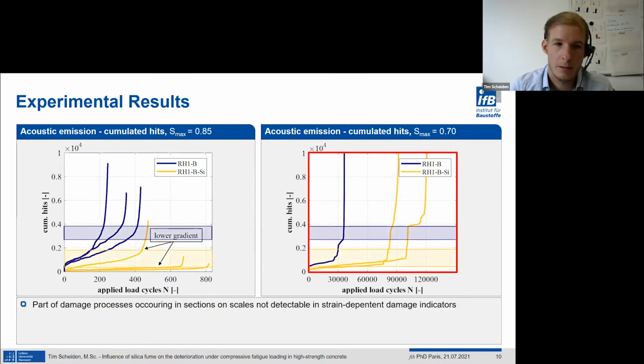In addition to the stepwise curves for the lower stress level, there's also a characteristic range of hits up to where an increased damage activity occurs. Here in blue is the range for the concrete without silica fume, here and here. And in yellow, the range for the concrete with silica fume. The ranges are different for each concrete and furthermore stress independent, so that this range is valid for both stress levels.